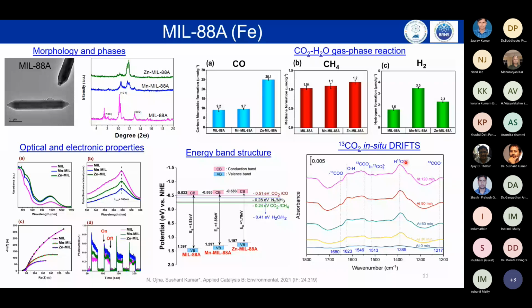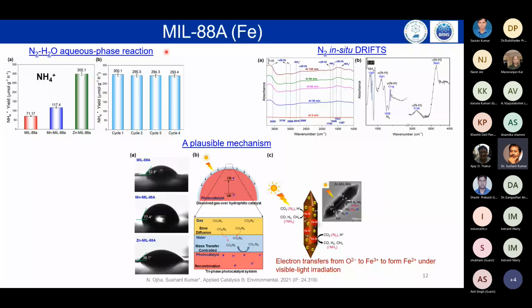And then we did it for the ammonium ion also, and with that we have seen that the zinc is again performing. We did the in situ DRIFTS, and we have seen the stretching vibration and also the bending vibration. So both of those of NH were present, and then we zoomed in to show you in a better way. This is what we have seen.